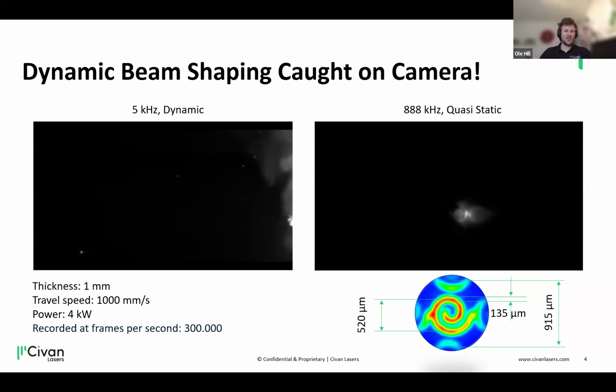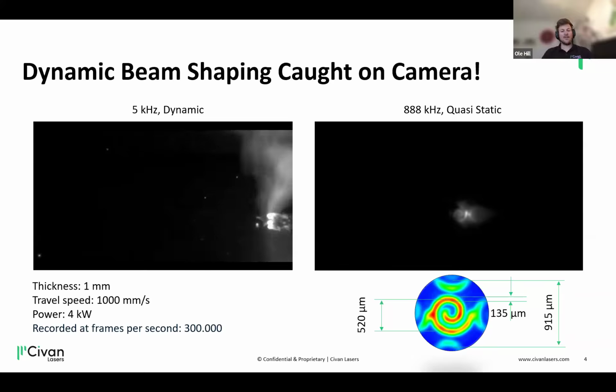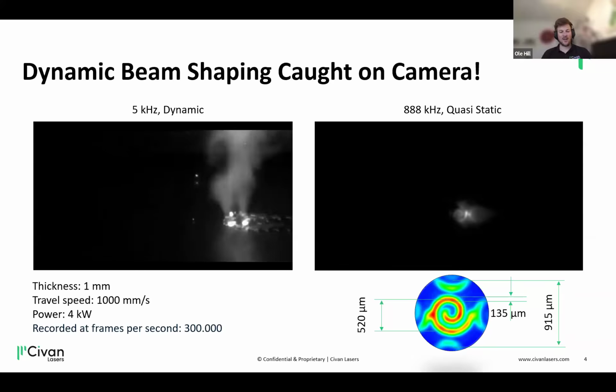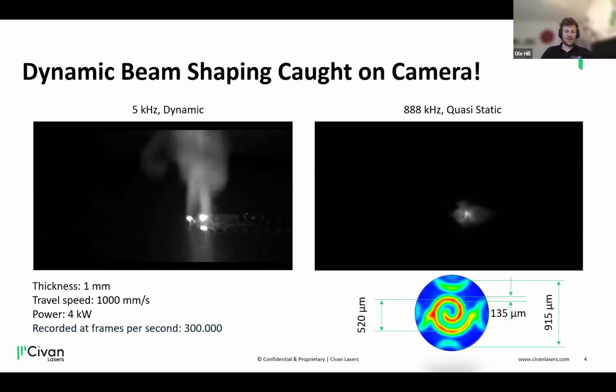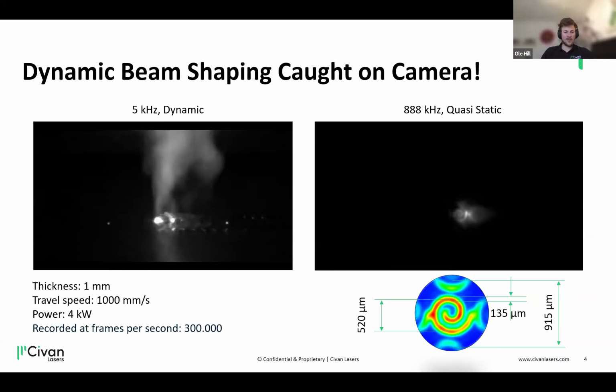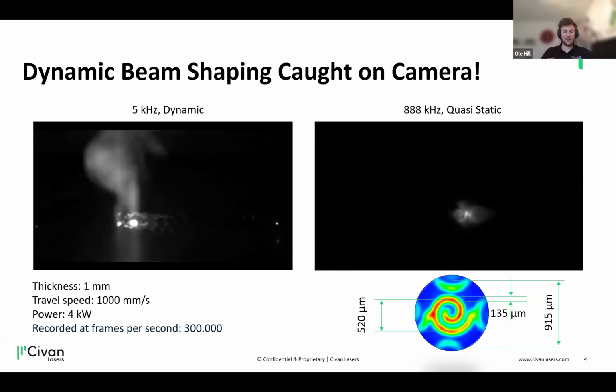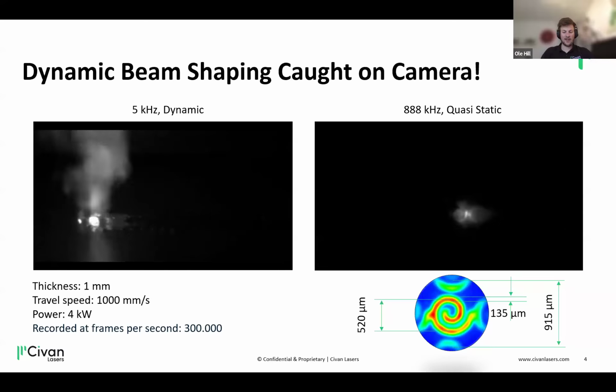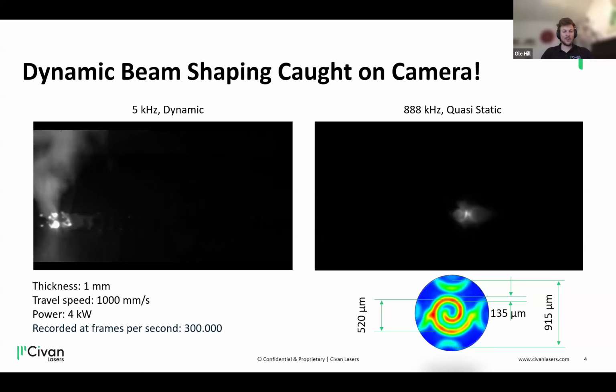First, let me show you what the real dynamic beam shaping can look like on a high-speed camera. On the videos I will show you now, you can see a spiral, which is depicted on the lower right. And it is done in a way that each point of the spiral is projected one after another. And then this results in a very dynamic melt pool. And you can even see it's like a circle from the inside to the outside, exactly like the spiral that we programmed for this weld.